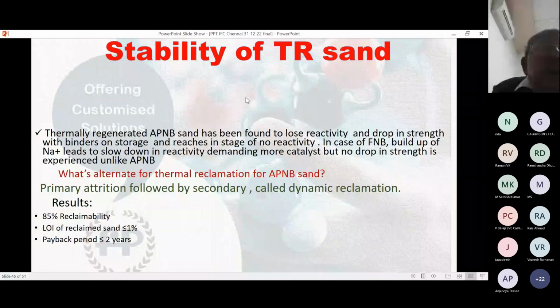This is an observation. Thermally reclaimed APNB sand, or Alphaset sand, has been found to lose reactivity and drop in strength with binder on storage, and reaches a stage of no reactivity. Of course, I should add that I have not studied sand from all the foundries, but a couple of foundries we have studied and found that reactivity decreases to a point of no reactivity along with the binder. In the case of Furan, buildup of sodium leads to a slowdown in reactivity, demanding more catalyst, but no drop in strength is experienced, unlike Alphaset.